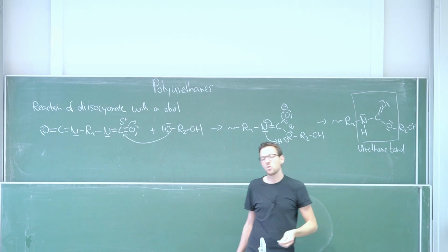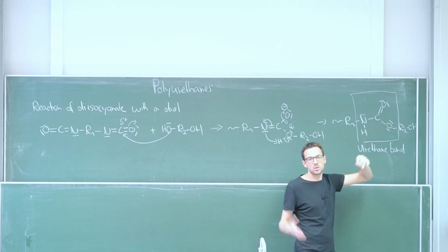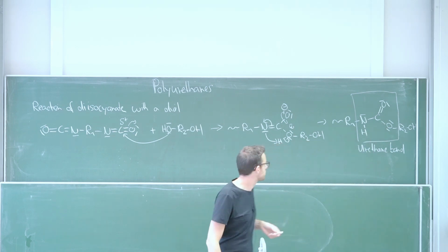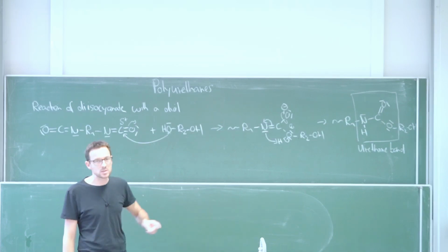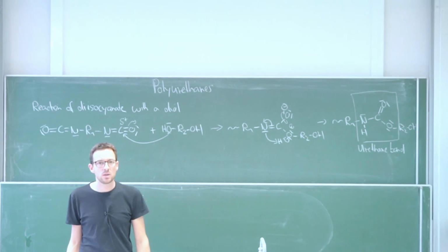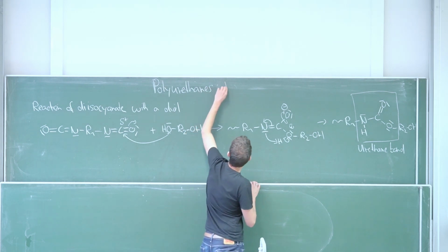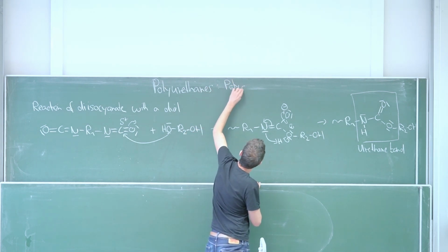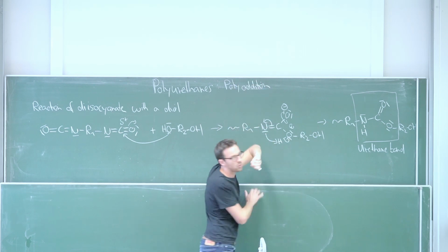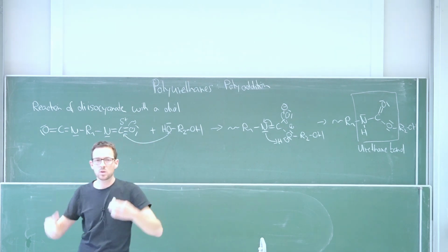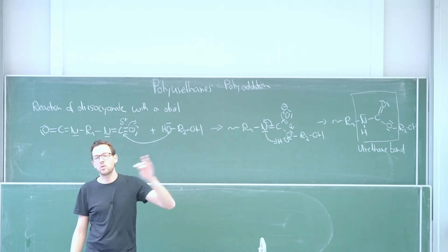So again, a bit similar to a mixture of an amide bond and an ester bond, just in one single molecule. Okay, now interesting, and compared to polyesters and polyamides, we do not release anything from the molecules here. So there's no water being released, and this is why this reaction is known as or called a polyaddition, as opposed to a polycondensation, where you condense 2 molecules and release water. Okay, this makes it easier for this reaction to occur because you don't need to bring the equilibrium in a certain direction.